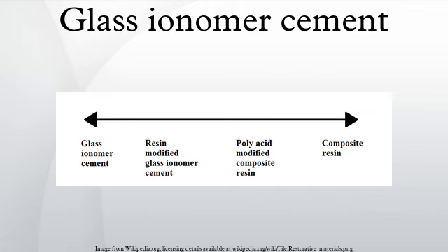Conventional glass ionomer restorations are hence also difficult to manipulate as they are sensitive to moisture imbibition during the early setting reaction and to desiccation as the materials begin to harden. Although it was believed that the occurrence of the resin polymerization in the modified materials reduces the early sensitivity to moisture, studies have shown that the properties of the materials changed markedly with exposure to moisture. Whether it is necessary to place a protective covering on resin-modified glass ionomer restorations remains controversial.